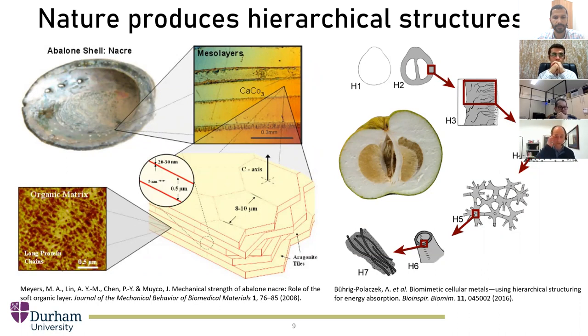And he found that there is a common length scale. When you look at the fibers of those feathers, they have a common feature at some point, which he said maybe is something important about turbulence or how things work. So yes, his group looked at different biological structures, and this paper is like 13 years ago when they looked at the shells. And the main feature that they reported was that there is this interplay or contrast between stiff tiles and soft matrix. And yes, maybe the key benefit of that is that it forces crack deflection.